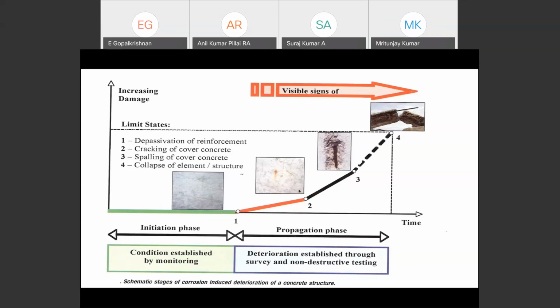Moving to the second stage, the development of corrosion, which occupies a volume significantly larger than the original steel. The induced tension in the cover concrete leads to the cracking. When the steel bar occupies a volume of 3 to 6 times, even more than 6 times, of the original steel, definitely the cracking happens to the cover. In stage 3, widening cracks facilitate the penetration of moisture and aggressive substances into the concrete, promoting a faster rate of corrosion, eventually leading to spalling of cover concrete. This has happened in stage 3.